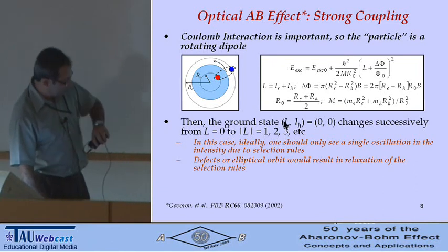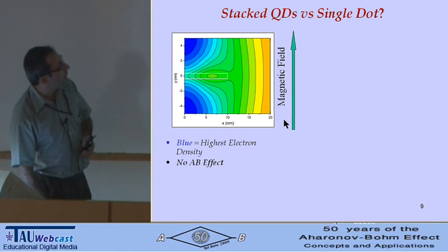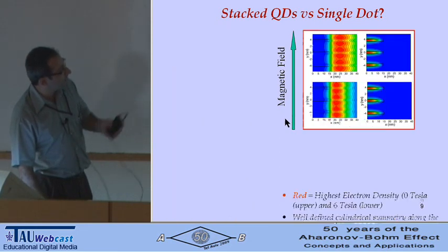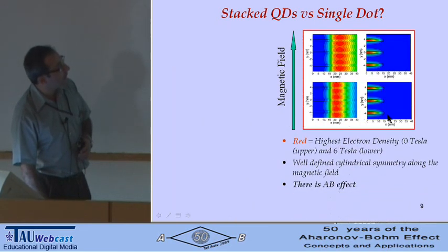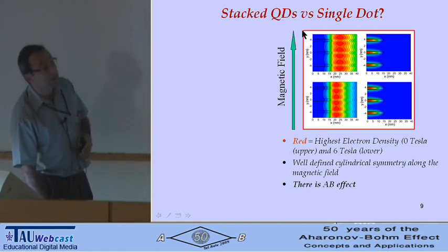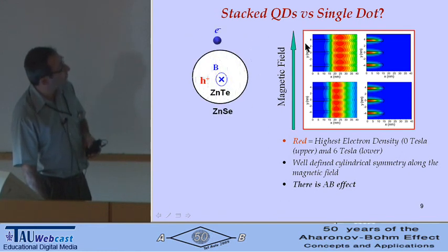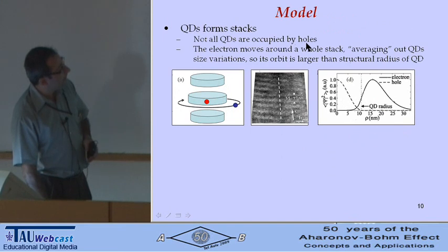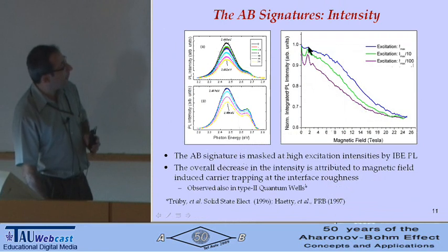And before I show you the data, I will quickly go through why single dot versus stacked dot. The single dot I already showed. However, if you have a stacked dot, you can do, again in a single particle approximation, a calculation and show that actually the electron wave function would not sit on the top of the quantum dots. It would be shifted to the side. So if you apply a magnetic field along the growth direction, you will have perfect cylindrical symmetry to see the electron motion. So those are details of the model. Because of time, I will skip it. And I'll show you the data.